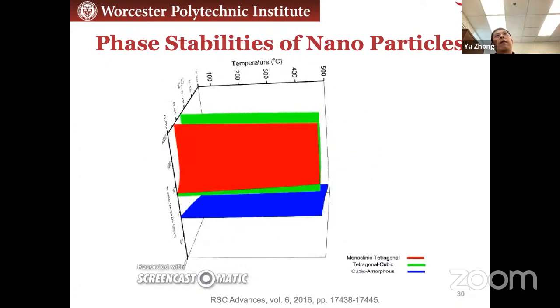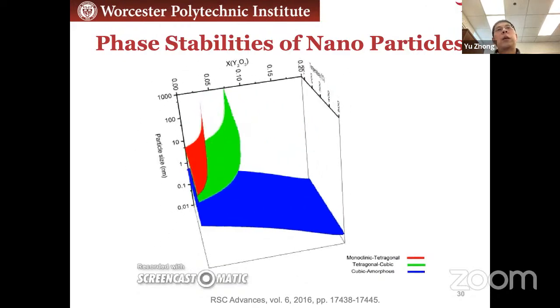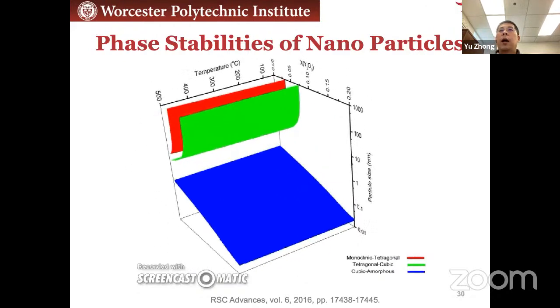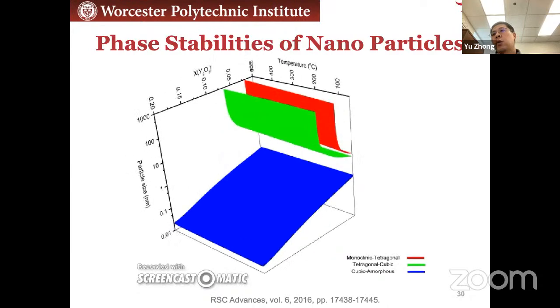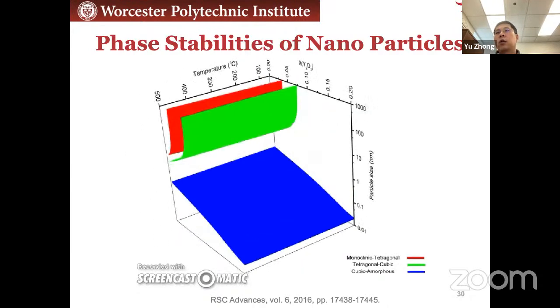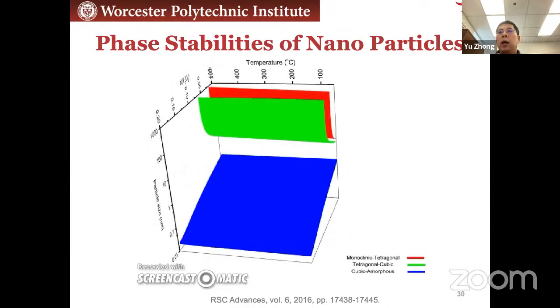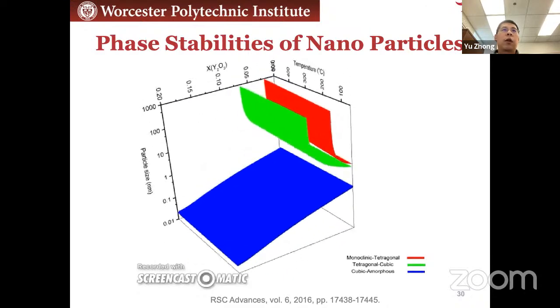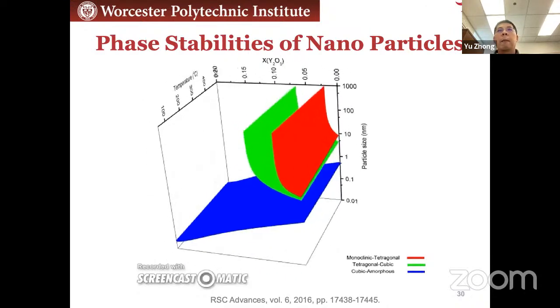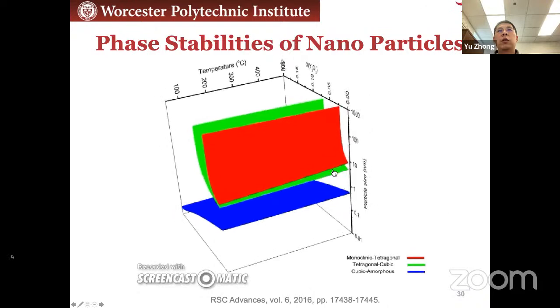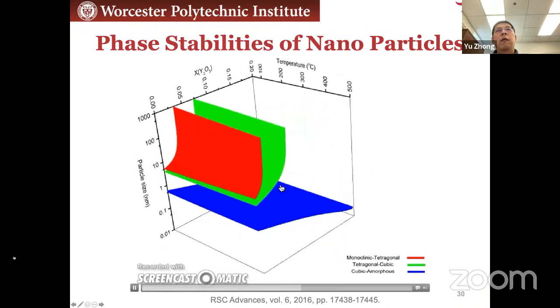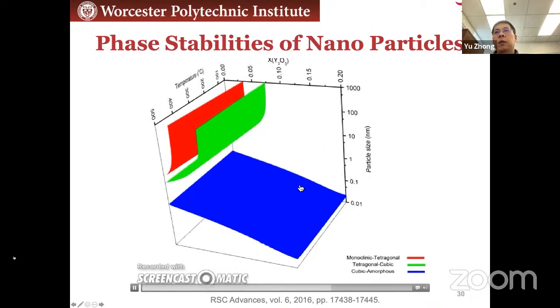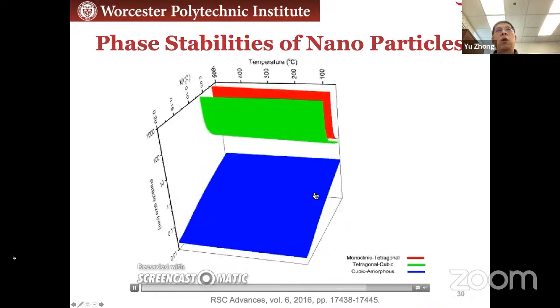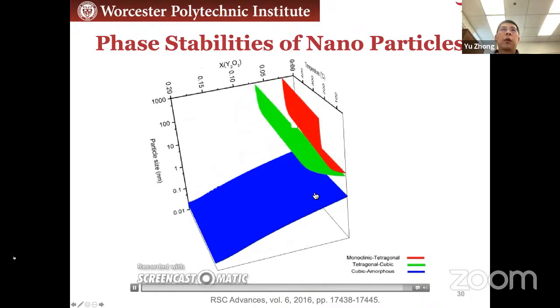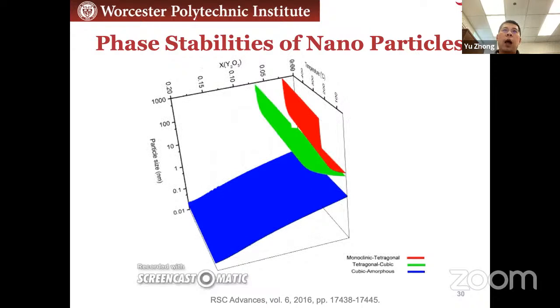So this is what we have done on the yttria-stabilized zirconia, and there are several different crystal structures there, like monoclinic, tetragonal, cubic, even an amorphous phase. And we can show you the boundary of those phase transformations. So then you will know if you change composition, you change your particle size,